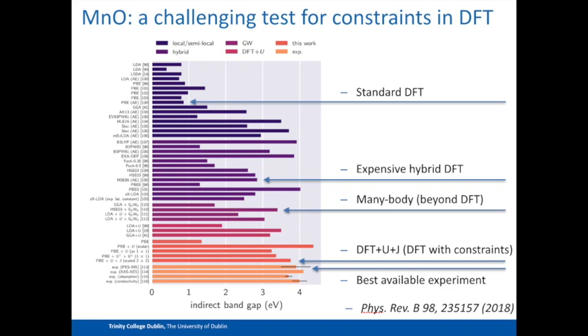And that's where we come in, my research group. So if we look at manganese monoxide, which is a very challenging system, it's not unlike the parent materials for certain high temperature superconductors. Standard density functional theory gives you absolute garbage basically for the band gap. So it gives you a large spread of results depending on which version of density functional theory you use, and they all underestimate the band gap with respect to the experimental band gap, which is down here around 4 electron volts. You can use a very expensive version of density functional theory.